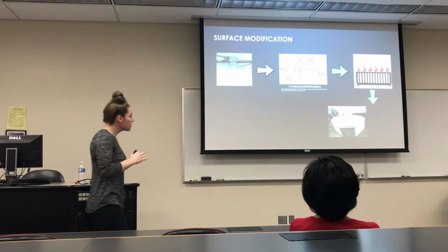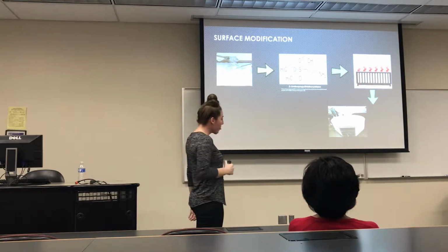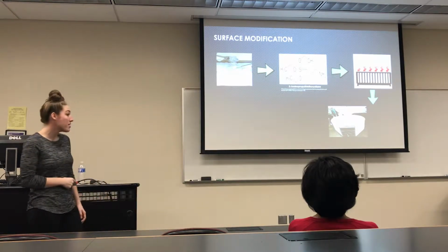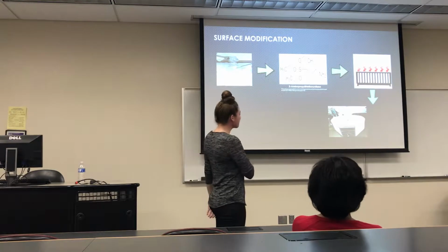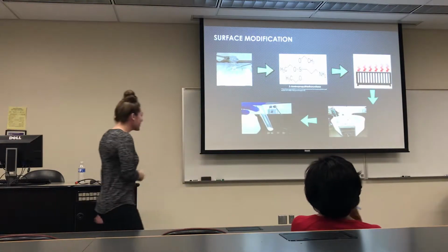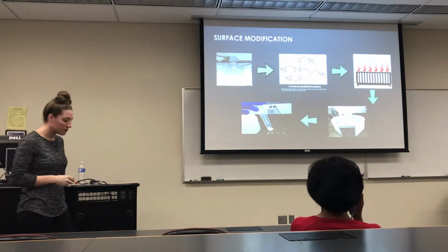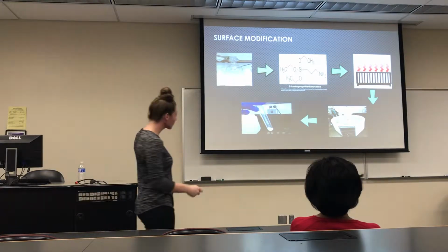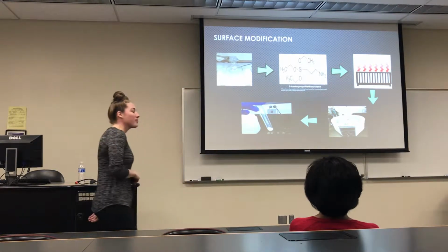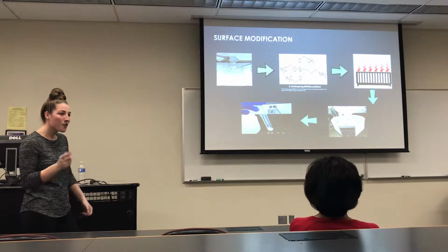Following this, we then can purify this solution because we want to make sure that we don't have any excess APTES in solution. So we can actually centrifuge it, and this was a little bit time consuming. This was 9 centrifugations of 10 minutes, and then redispersing within water. So that was fun. But eventually what we're left with is this nice pellet which we can redisperse in solution to use later on.